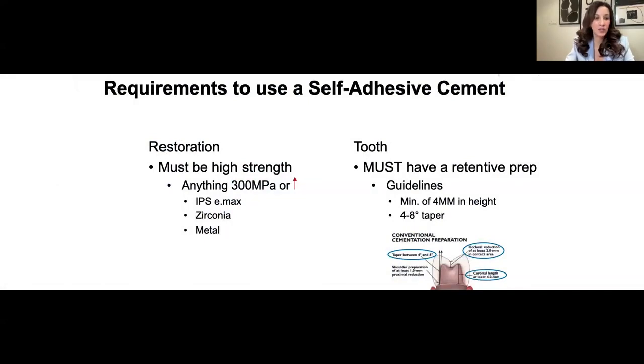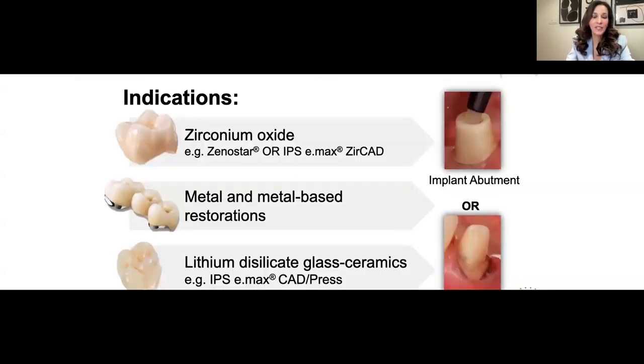Your restoration must be high strength. So it could be anything like an Emax crown, a zirconia, even a metal crown. The tooth must be retentive. So you want to have a 4 to 8 degree taper and at least 4 millimeters in height. And the indications, you can use self-adhesive cement or conventional cement for zirconia, for metal-based restorations, or for Emax restorations.